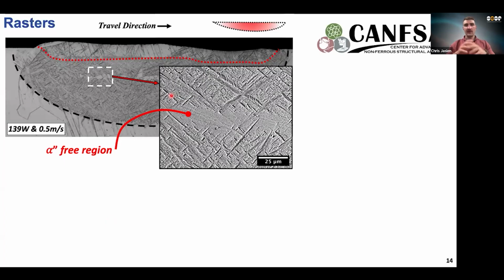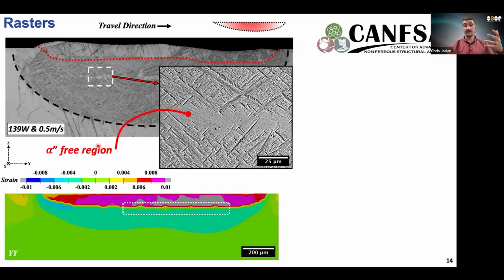And so an interesting thing that we didn't see previously is that just midway in between this heat affected zone, we see a very delineated region where we don't see any of this alpha double prime transformation. So it's an alpha double prime free region.